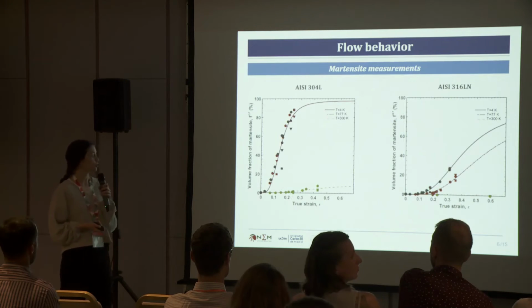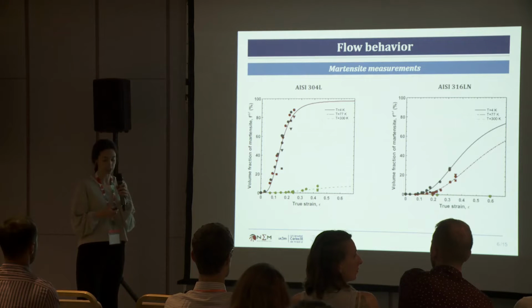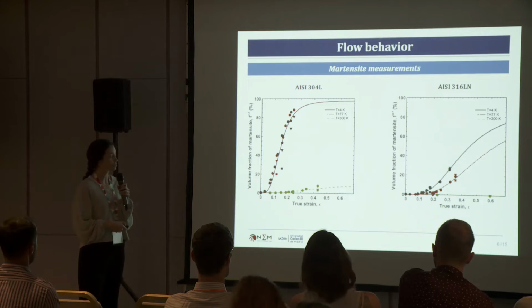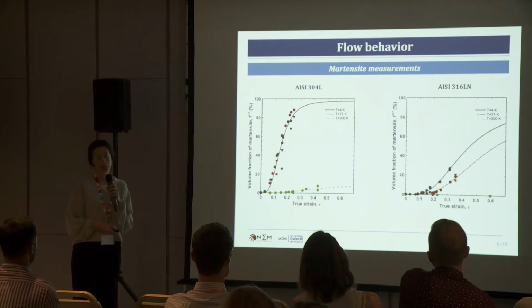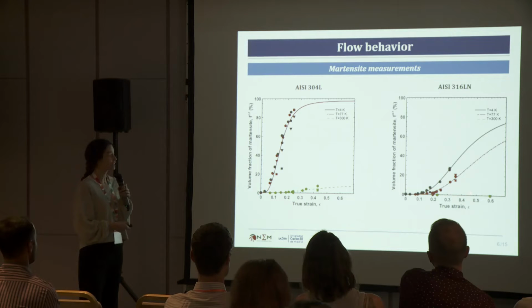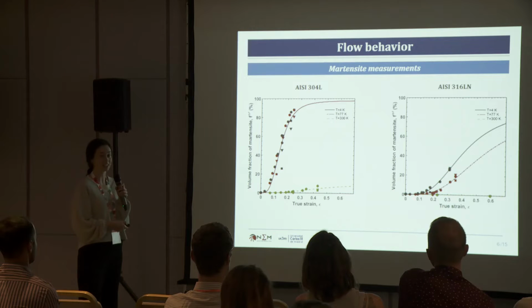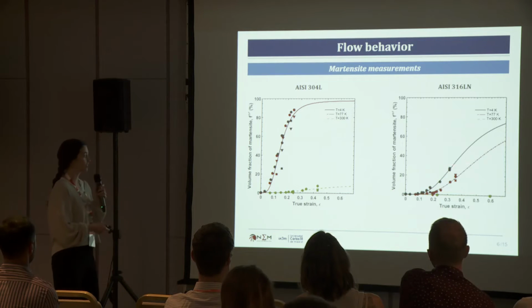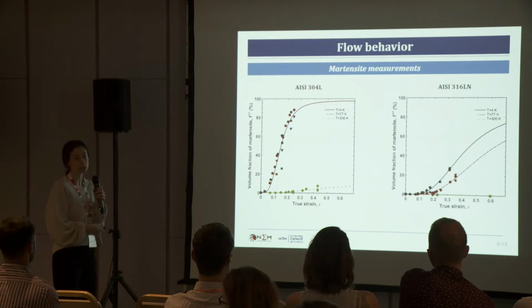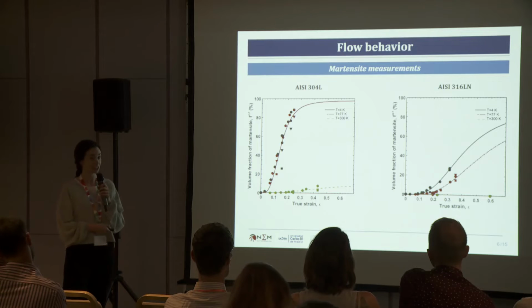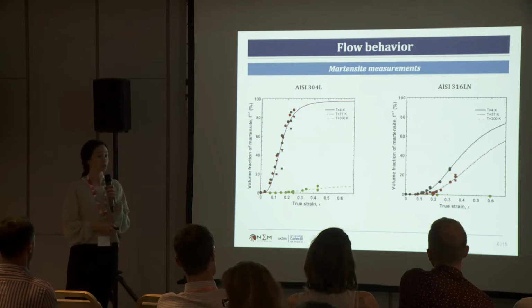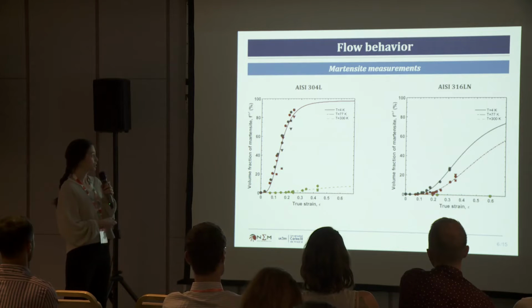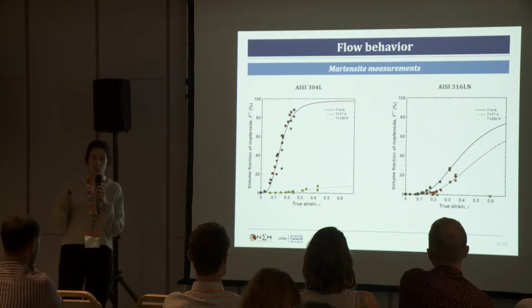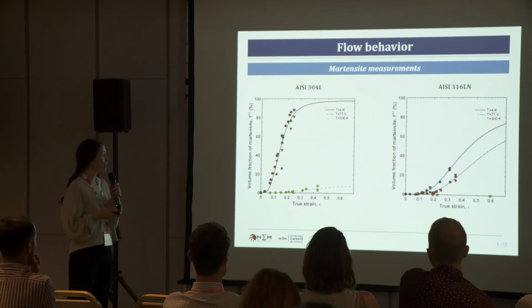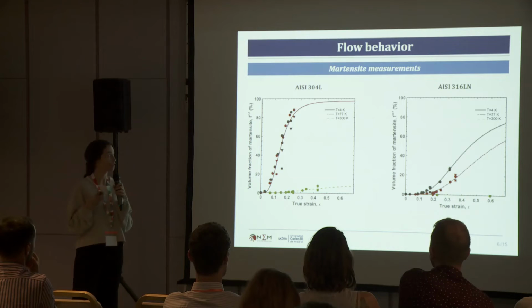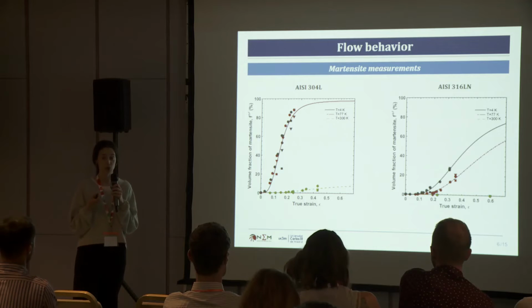So let's see first the evolution of martensite for these two grades at the three different temperatures. And as we can see here, for the AISI 316LN, at room temperature in gray, we don't have any transformation. But now at cryogenic temperatures, we do have a transformation. And this transformation goes faster at 4 Kelvin and starts earlier too. For the AISI 304L, you can already see, it's quite obvious, that the transformation is higher, it's more intense. At room temperature, we already have a transformation, and then at cryogenic temperature, it's quite extensive, you can see there. And what is also very interesting is that it's almost the same for the two temperatures, 77 and 4 Kelvin. This I will go back to later, so remember that. Very good, so I have already shown you, I have been talking about the flow behavior of the two grades.